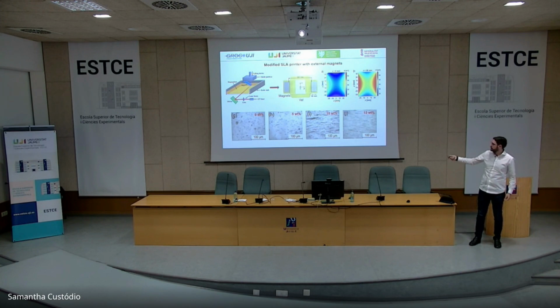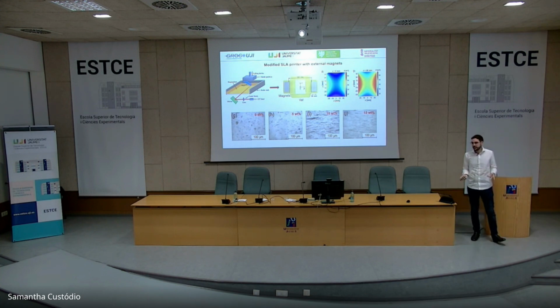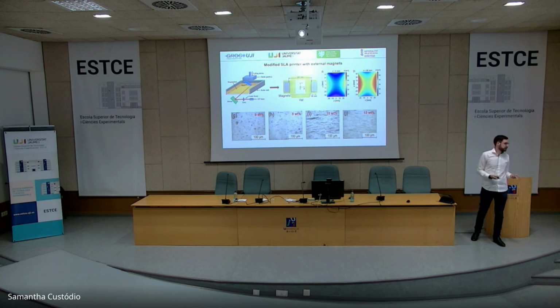When we increase this magnetic field, and we also increase the amount of acetone, because that's also changing the viscosity and the particles can move more easily or with more difficulty, we can achieve what we call nanostrands, these linear chains that we are forming that are aligning with the magnetic field. And when we are printing, this gets fixed in the material because we are solidifying the polymer. So basically during the printing, we are doing two processes. We are doing the printing, that is the standard, but we are also doing the alignment of the nanoparticles.